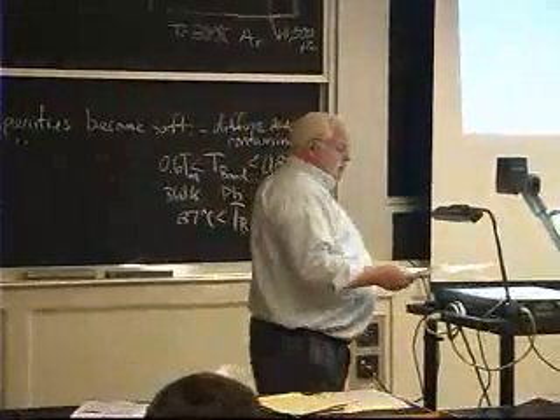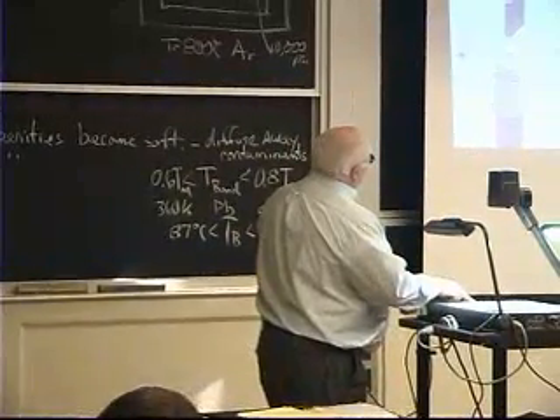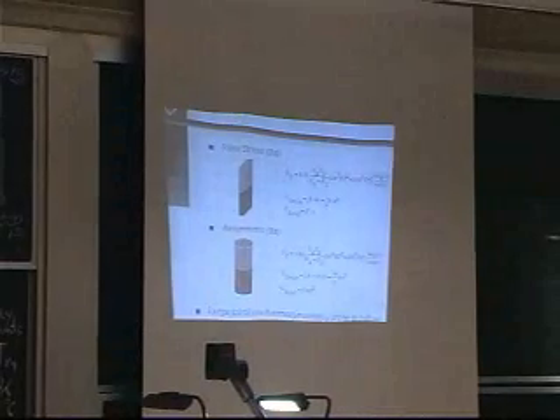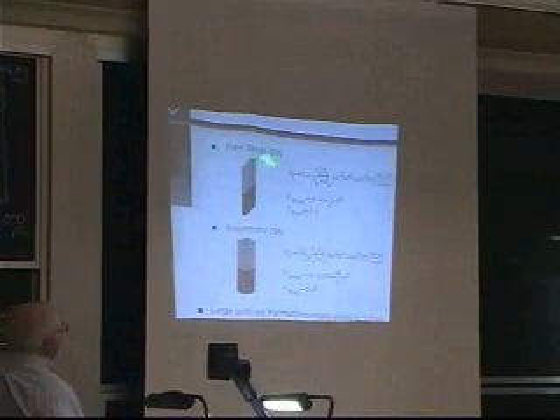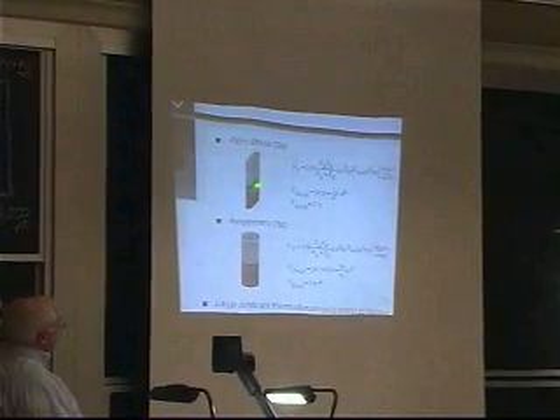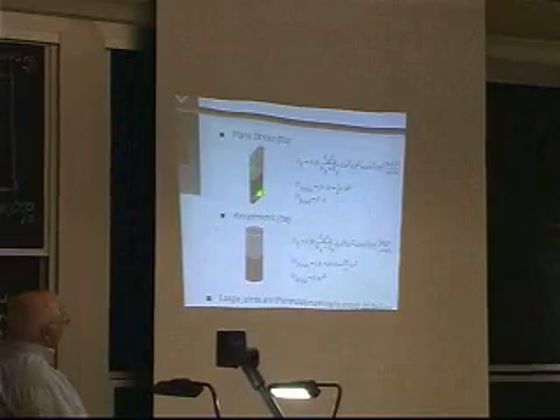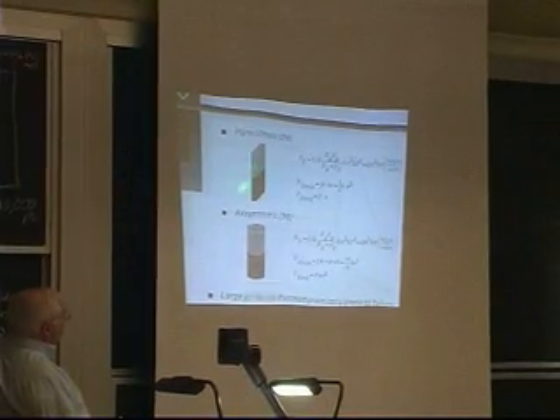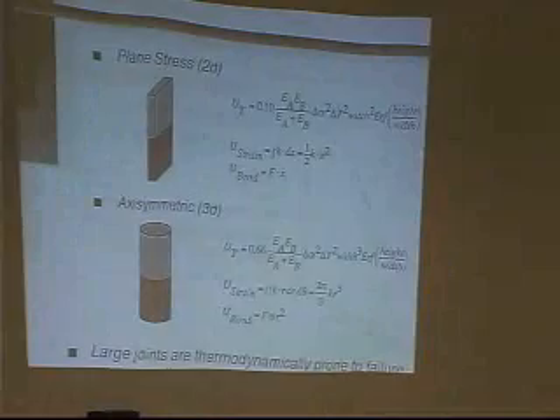Okay. Another problem with diffusion bonding is you have a problem if you're bonding dissimilar metals. If you're bonding titanium to titanium, there's no problem of dissimilar metals. But if I'm bonding two different materials, I've got a coefficient of thermal expansion mismatch, and I will set up residual stresses in that interface.